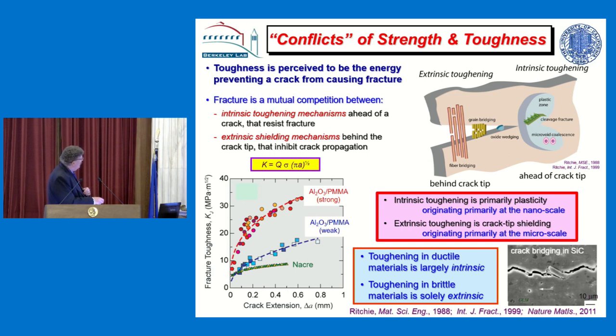But the interesting thing is that the notion of having damage behind the crack tip, or resistance behind the crack tip, gives rise to something called the resistance curve, or R curve. And this is an R curve. This is the fracture toughness of a material plotted against the crack extension. And you can see that the toughness will increase as the crack initially extends. That's due to the fact that as the crack extends, you get more of these mechanisms forming behind the crack tip, which makes it more difficult to move the crack.